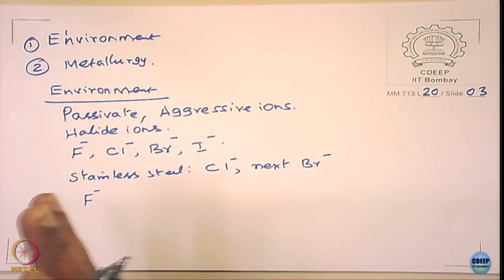Fluoride, see, if you have a passive film, if the passive film has to get damaged by these ions, the ions have to migrate in the passive films, right. They have to migrate and then form a complex. The migration depends upon what? The radius of the ions. If the radius of the ions is too big, then migration becomes very difficult. So if you take it that way, fluoride's ionic radius should be smallest as compared to chloride and bromide and iodide, but even then the fluoride does not cause severe pitting as compared to chloride for two reasons.